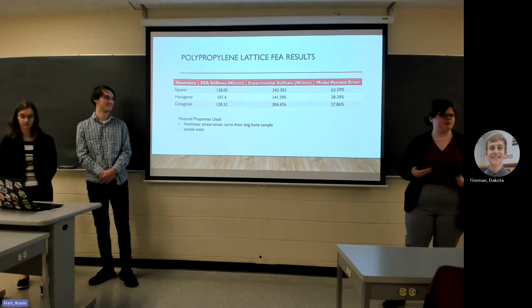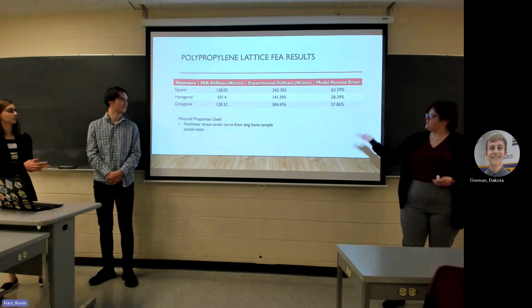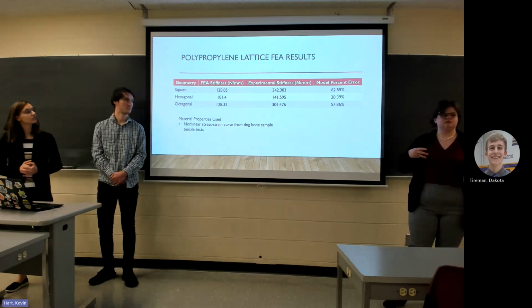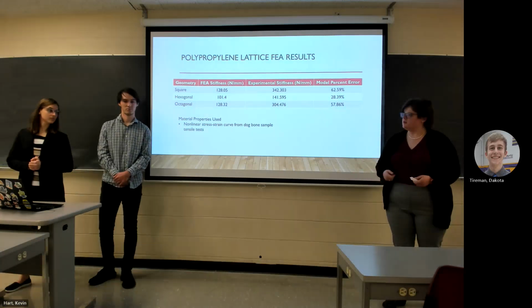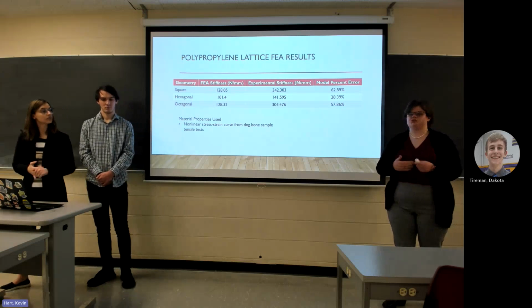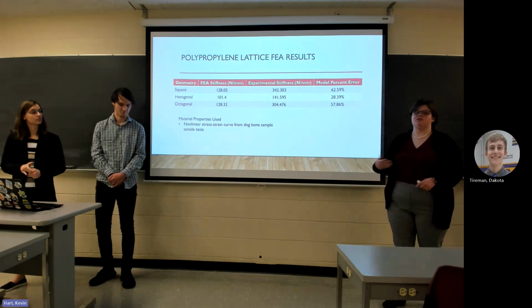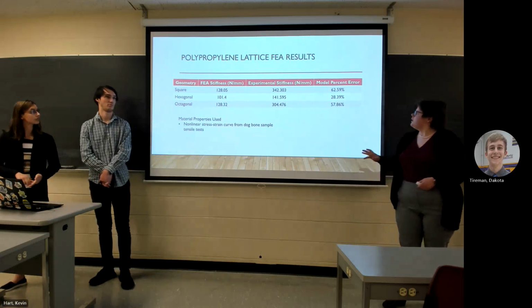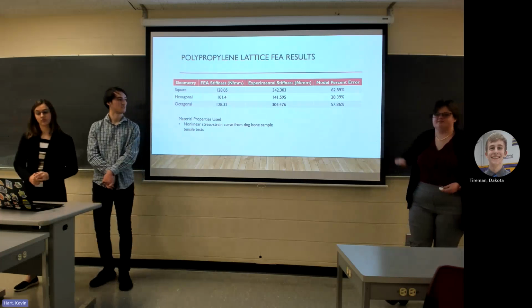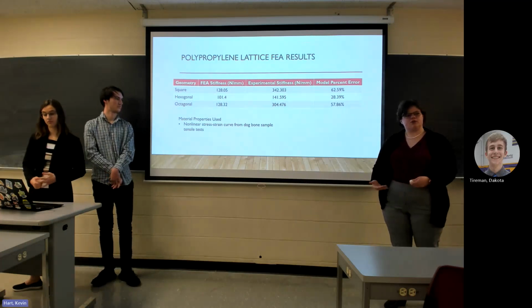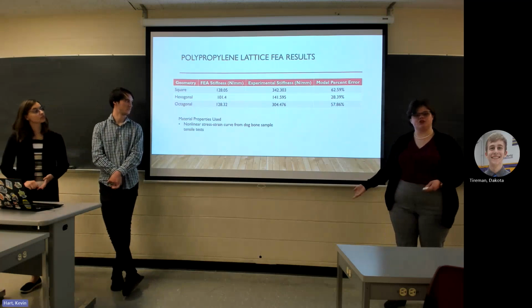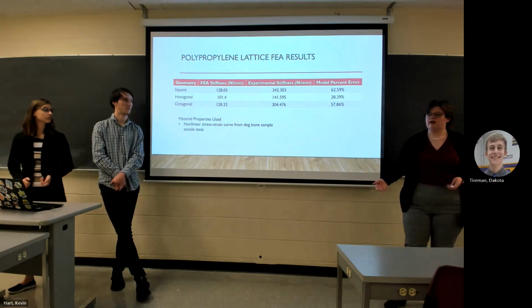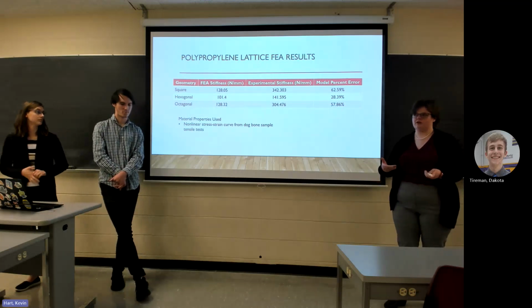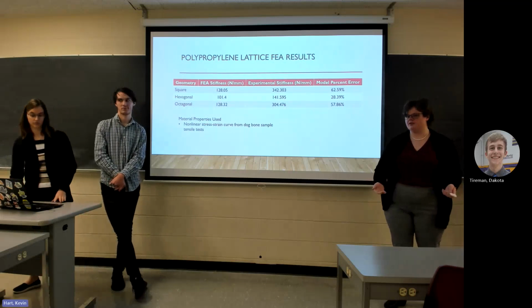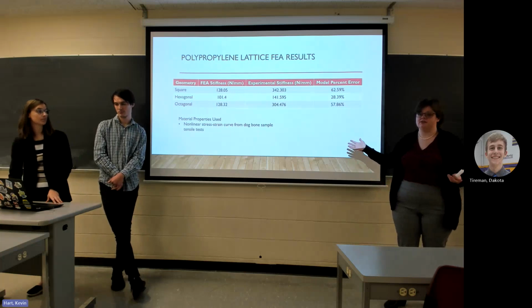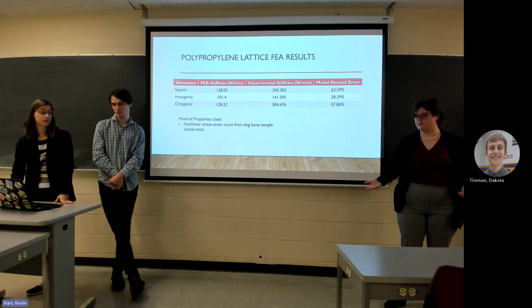The polypropylene has given us a little bit more trouble. This data was gotten using a nonlinear model for the polypropylene. We used experimental data generated from just regular tensile tests of printed polypropylene for a stress strain curve to input into ANSYS. But we were getting these massive errors, and we're not entirely sure why. So our next step in trying to get a validated model for the polypropylene structures is to go through and retest, as we're concerned that there may have been some issues in the printing or the testing of those specimens, because we were using a very similar or the same model in terms of boundary conditions as we did for the nylon 12 with polypropylene.